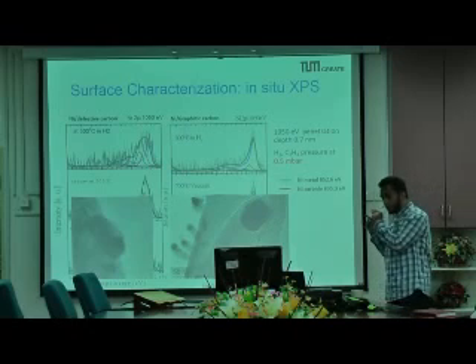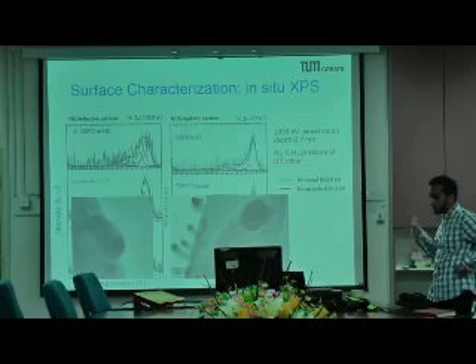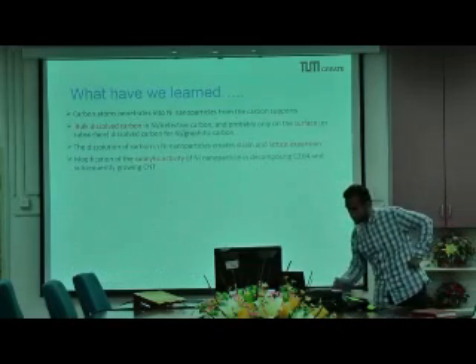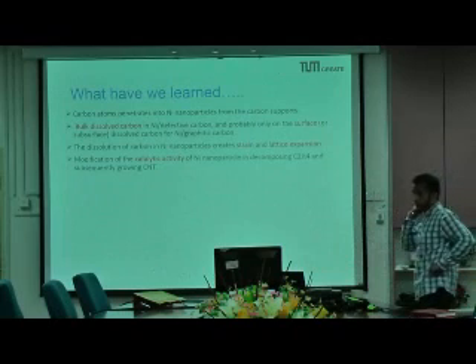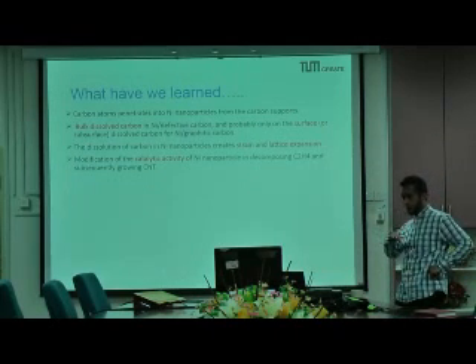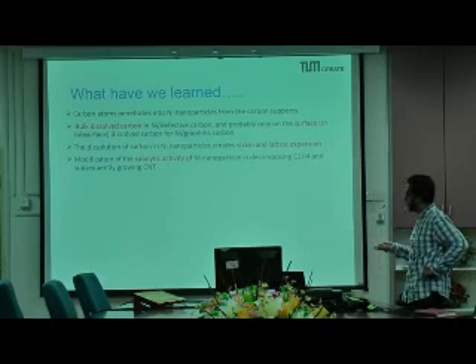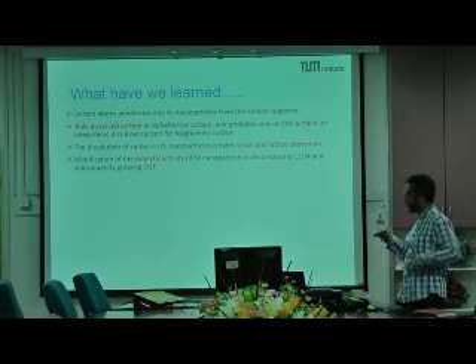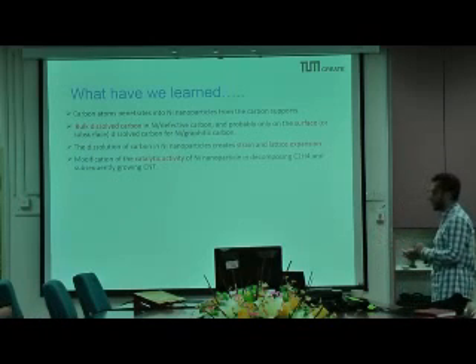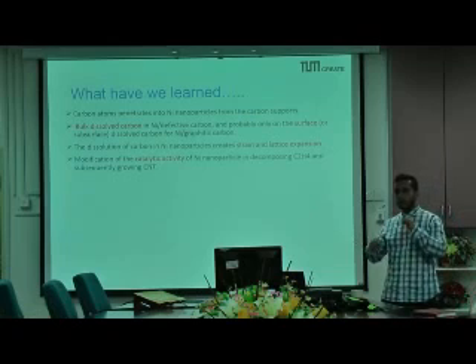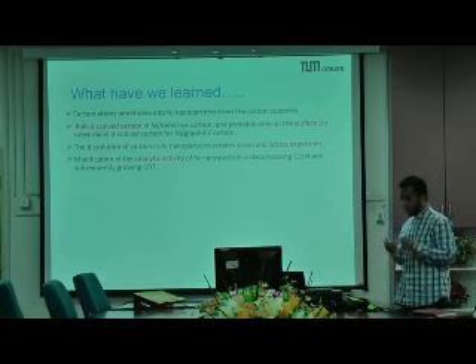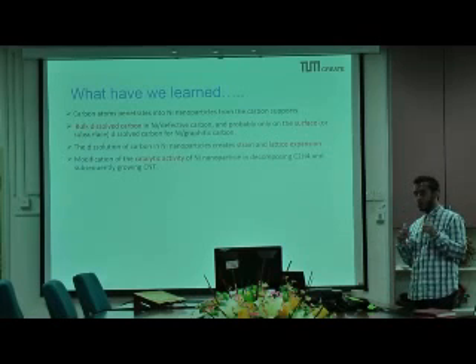The nanotubes growing from a graphitic support are quite well oriented, with the crystal alignment going into the nanotube-like structure. So what have we learned now? We know that some amount of carbon penetrates the nickel nanoparticles either during heating or during reduction. We know from the XRD that there's some amount of carbon dissolved in the bulk, mostly in the nickel on defective material. And this dissolution creates strains in the interface and in the nickel crystal structure, and this may cause the activity to change.